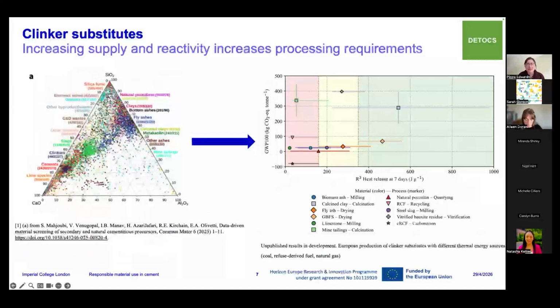So more reactive materials are likely able to displace more clinker for the same performance. To assess the reactivity of clinker substitutes, a common experimental method is called the R3 test, which uses a simplified hydration experiment to measure the amount of heat released and the bound water. Performance also depends on some physical properties like particle size and mix design. So predicting behavior of the clinker substitute materials is an ongoing research challenge.